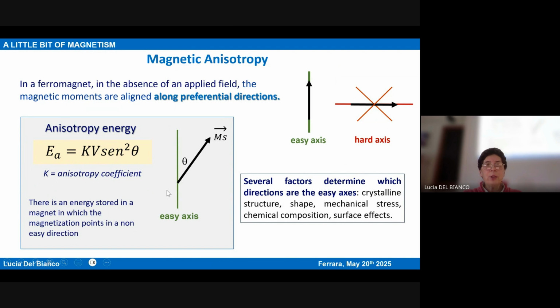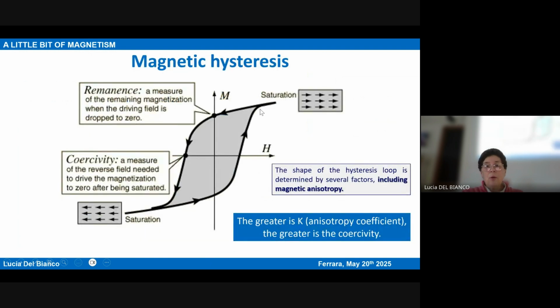And therefore, if you are in a situation in which the magnetization does not point along an easy axis, for instance, because you are applying a magnetic field which is trying to rotate the magnetization away from the easy axis, there is an energy loaded in your ferromagnet, which is called the anisotropy energy, which in the simplest form is given by this expression, where K is an anisotropy coefficient, which depends on the type of magnetic anisotropy that you are considering, which, let's say, predominates in your ferromagnet above the others. V is the volume of your ferromagnet, and theta is the angle between the easy axis and the magnetization. Therefore, it's clear that the anisotropy energy is minimized where the angle is zero.